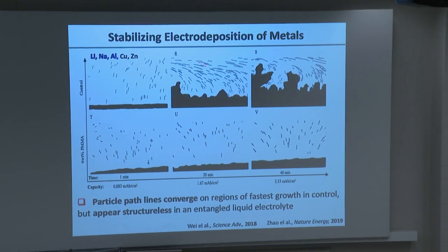If I look at the tracer particle lines, I can see that, in fact, the theory is right, that the tracer particles appear to point towards the bump, indicating that the fluid flows are, in fact, feeding the growth of the bump, as we speculated at the beginning.